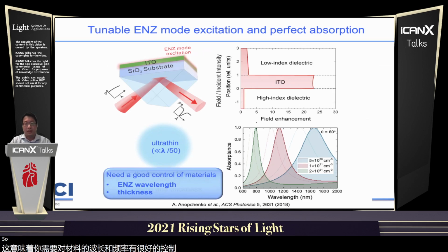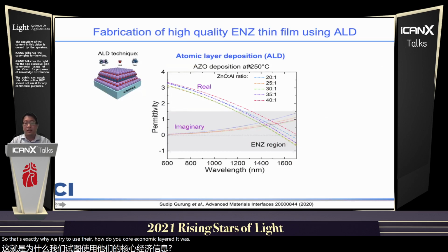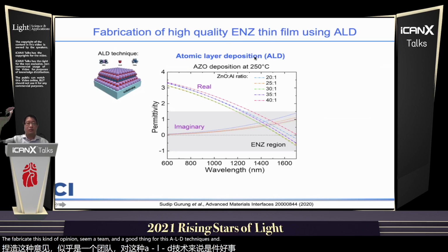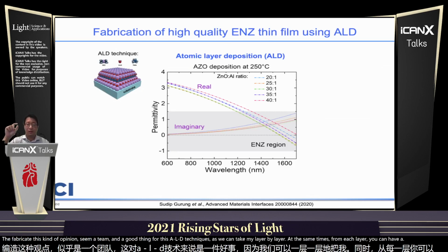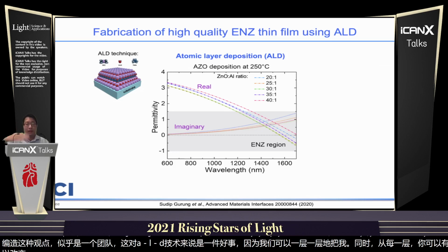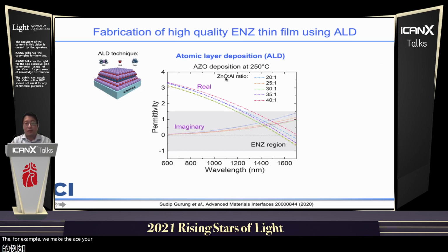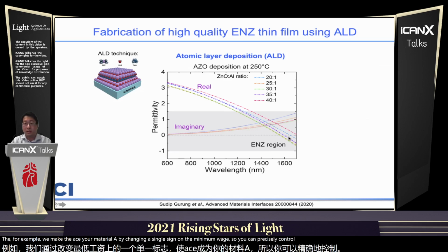So that's exactly why we use a technique called atomic layer deposition to fabricate this kind of ENZ material. The good thing about this ALD technique is that you can do it layer by layer, and each layer has atomic layer thickness. At the same time, you can change the property of each layer by using this ALD technique. So for example, we make the AZO material, and by changing the zinc oxide to aluminum ratio, you can precisely control this ENZ wavelength.